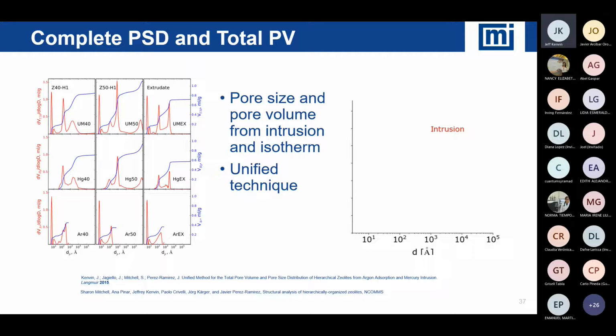How do we bring the two together now and unify the pore size distributions so that at the end we've got one coherent understanding of the material? On the left side, you see the effects for different zeolites. So the bottom row is adsorption. The middle row is, if we look at intrusion, and notice the difference between the bottom row and the middle row, that in adsorption, I could see small pores and mesopores quite clearly. In intrusion, I could see mesopores and macropores.